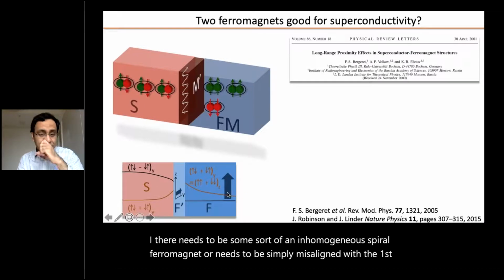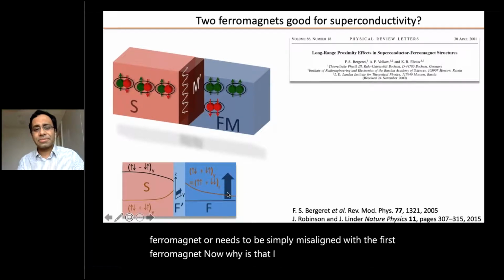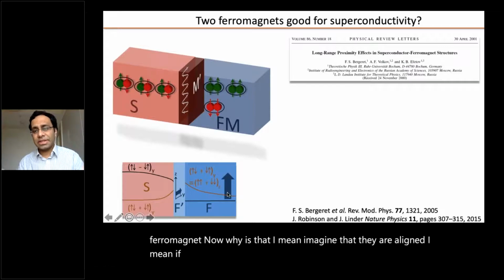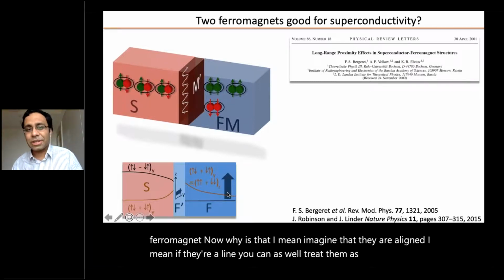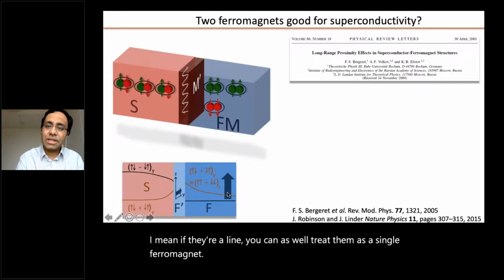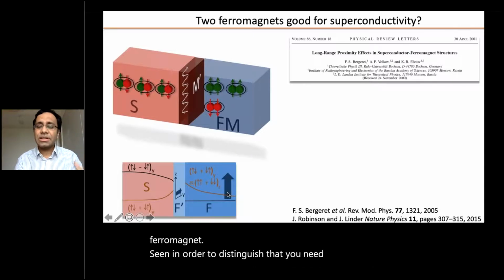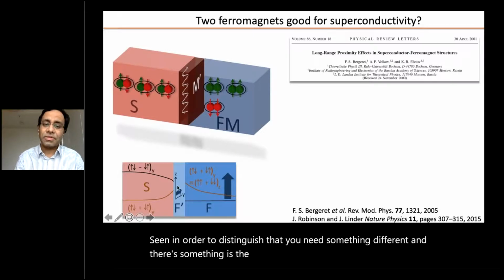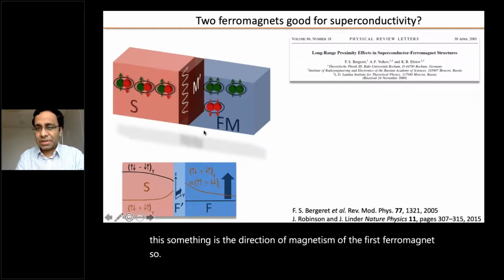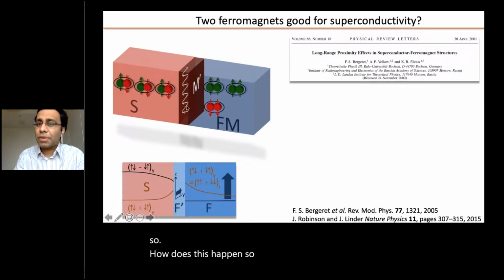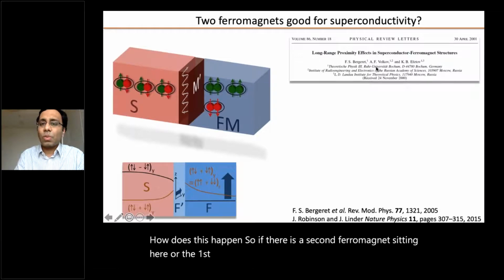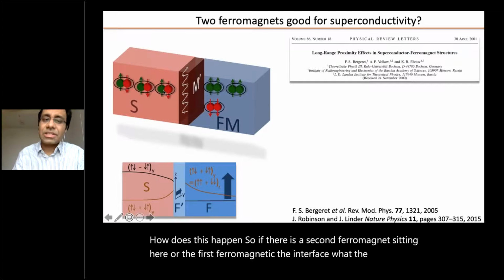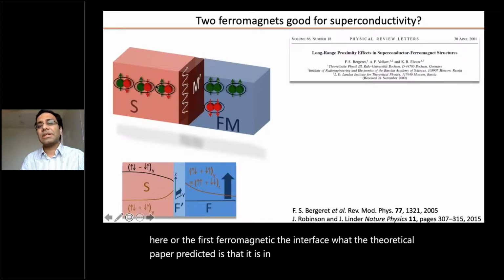Now, why is that? Imagine that they are aligned. If they're aligned, you can as well treat them as a single ferromagnet. So in order to distinguish that, you need something different, and this something is the direction of magnetism of the first ferromagnet. So how does this happen? If there is a second ferromagnet sitting here, or the first ferromagnet at the interface, what the theoretical paper predicted is that it is in principle possible to convert a singlet Cooper pair into a triplet one.